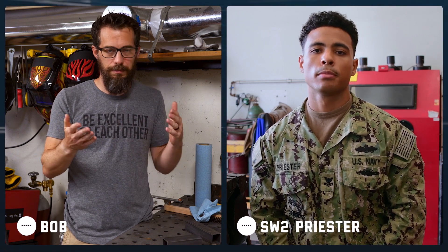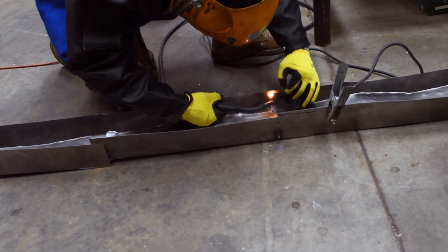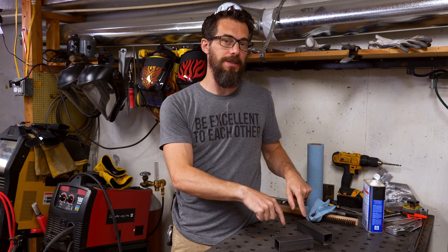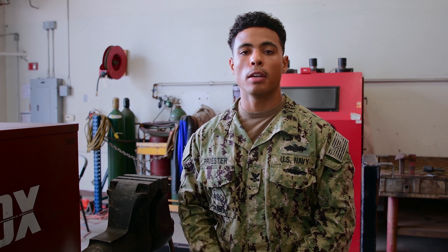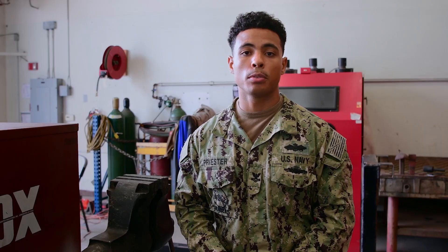So what makes it more difficult than non-vertical welding? With vertical welding, the reason why it's so difficult is because as you're welding, the molten metal is going to drip down through gravity, opposed to the easier position which is flat welding. What prep work do we need to do to these pieces to get ready to weld them? The first thing you want to do is make sure you clean them off — use a grinding wheel or a metal brush — then set them up. I'll put on a tack weld and then you can put them in a vise. As you're going with the weld, you want to keep your rod at a 45-degree angle and just stay nice and smooth.